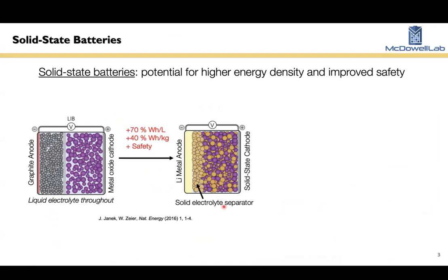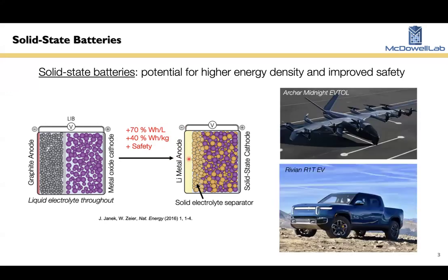So moving to a solid-state battery, you basically just replace that liquid with a solid material that still conducts ions, has a high ionic conductivity. And this could enable you to use new electrode materials with higher capacity, like a lithium metal anode. And if you can do that, you'll boost the energy metrics of the cell. So this shows basically about a 40% specific energy boost and a 70% energy density boost. And you'll potentially get improved safety as well, because of the lack of a flammable liquid electrolyte.